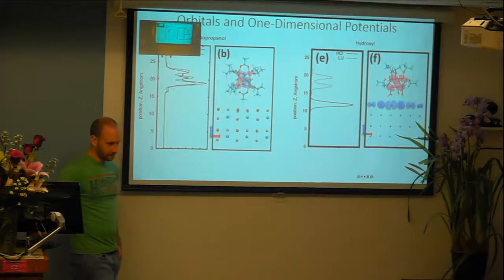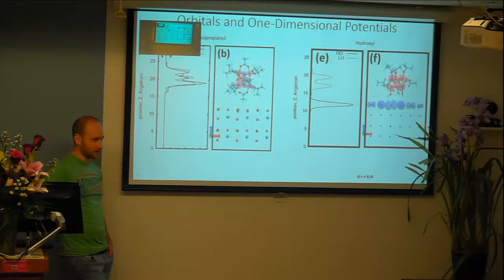Okay, so you're assuming a fixed energy, that you're exciting the case where the HOMO and LUMO are on one material. When your HOMO is on one material and your LUMO on the other material, this transition is optically inactive. You cannot excite such a state, right? You can excite the states which are either both localized on the perovskite, and then it would be a perovskite transition, or both localized on the quantum dot, and then this would be your quantum dot transition. And then the idea is when you excite one material, the charge transfer should go not between HOMO and LUMO, but inside the band, from an unoccupied state if it's electron transfer, or from an occupied state if it's a hole transfer.